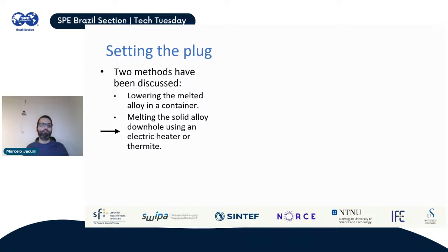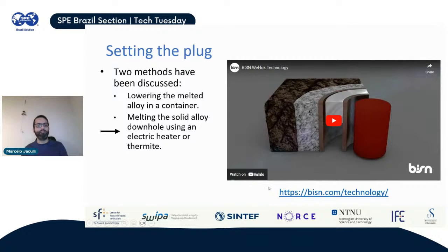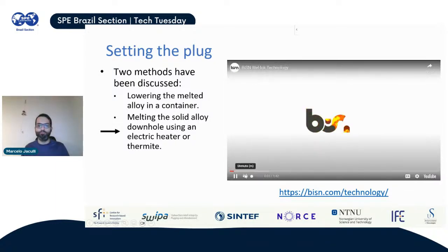To settle the plug, the literature, not just the literature, but patents that were made for this technology, basically propose two different methods. One would be pouring the melted alloy already inside a container and then lowering this into the well. Or you have the option of melting the alloy inside the well. So you lower it in the solid phase, and then you melt it downhole using some electric heater or some thermite reaction. So I have a video here from one of the service companies. You can visit them on their website, but I do not represent them. I just think that the video is very good at showing this.